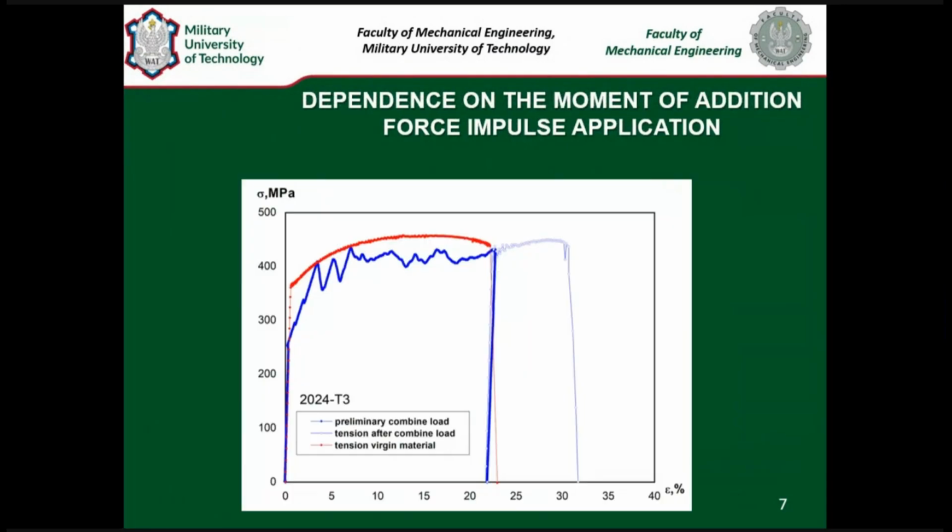Very important is the moment of application. If you apply the additional force impulse at nearly 0.7 of the yield stress, we have maximal plasticity for this element.